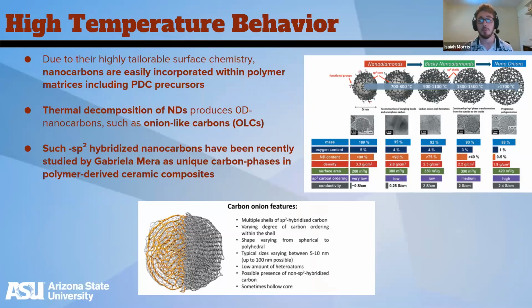But when it comes to forming a PDC, you have to think of that last step, the pyrolysis, the high temperature treatment. And if we are encapsulating a nanodiamond within this polymer matrix, then how will that affect the nanodiamond? Will the temperature affect it, if at all? Well, it does. And as you can see in the figure here to the right, you can see exactly how. Nanodiamonds actually exhibit thermal decomposition as you increase their temperature treatment.